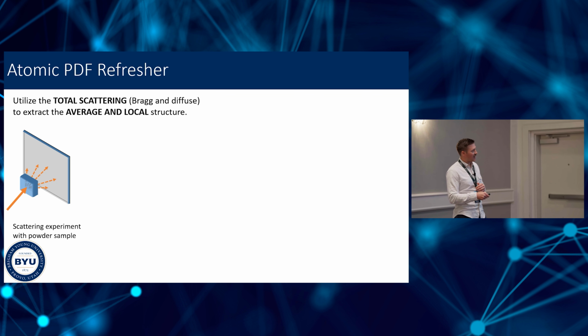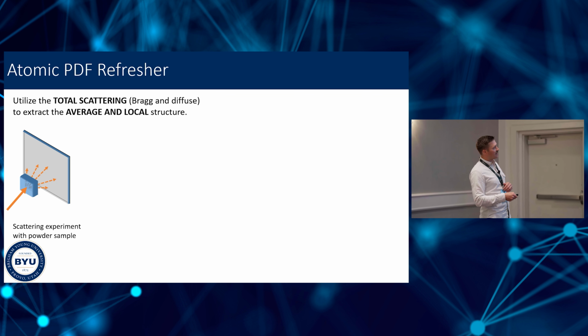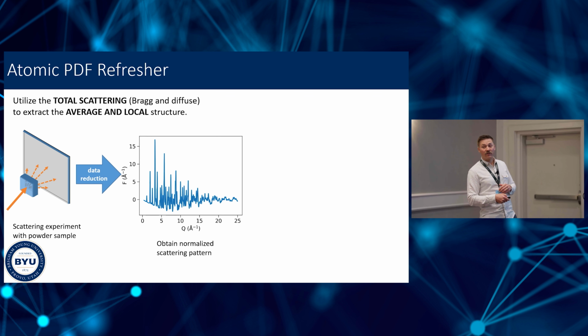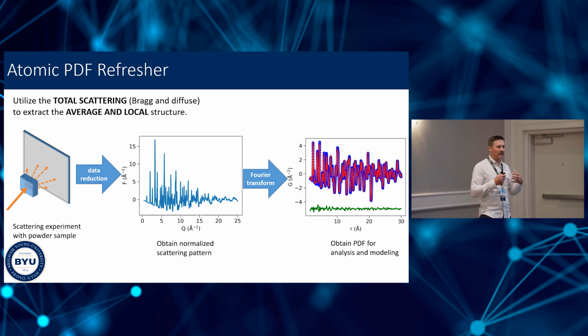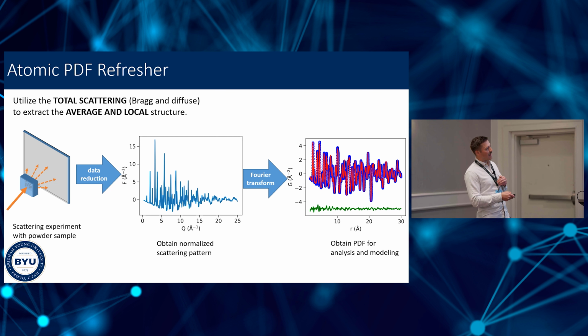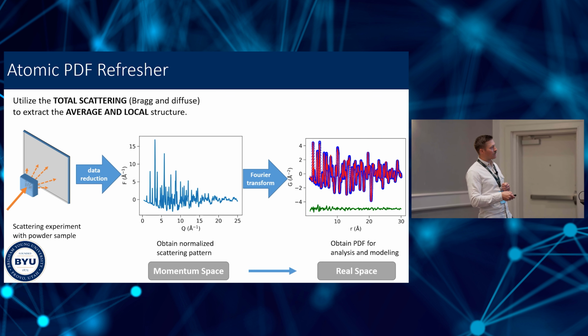Typically this is done with a powder sample, do a scattering experiment, and the key thing is to collect our scattering pattern out to a large momentum transfer. This is 25 inverse angstroms shown here. So that we can then do a Fourier transform into real space to yield the pair distribution function. All right, so now the horizontal axis here is real space distance in angstroms, and peaks in our PDF mean that there's a high likelihood of finding two atoms separated by that distance. All right, so we have moved from momentum space into real space, and this is giving us a map of the local interatomic correlations in our material, regardless of the long-range average periodicity of the crystal structure. The local structure is represented here in the PDF.